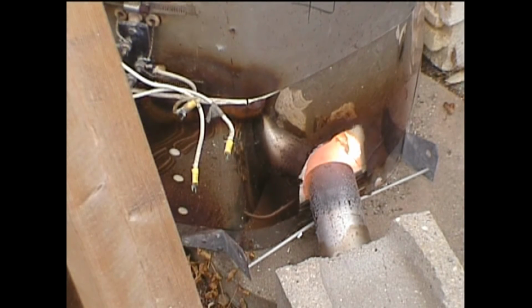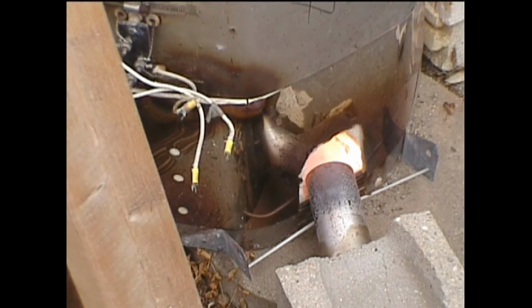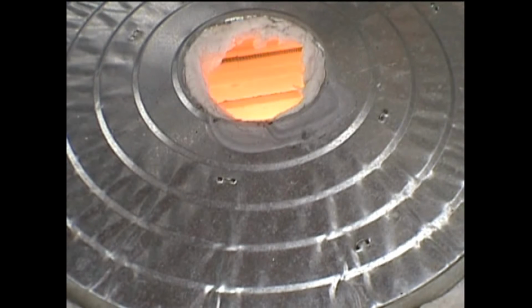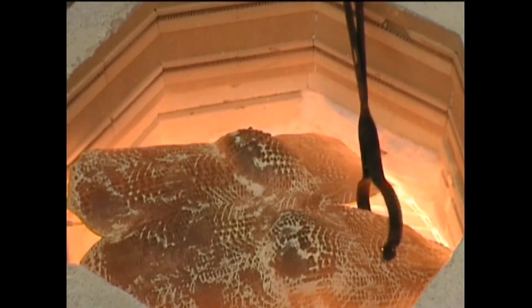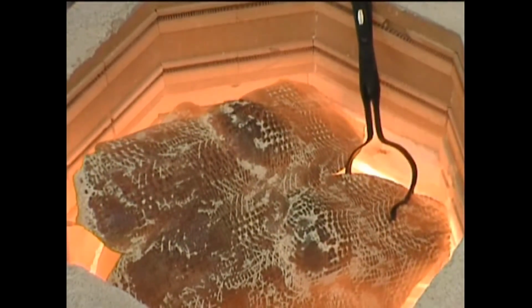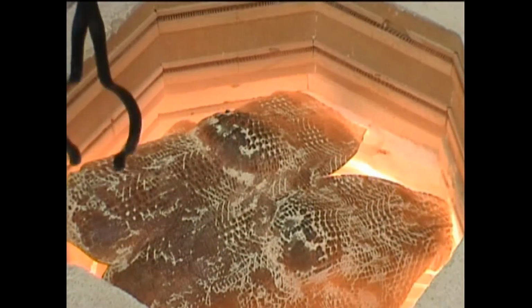At 1200 degrees, I turn on the shop vac and increase the airflow. At this point, the temperature rises very rapidly and will reach about 1850 degrees in 10 to 15 minutes. At 1850, or whatever temperature your glaze material needs, you can open the kiln lid. You can reach inside with your tongs and remove the piece you're working on.